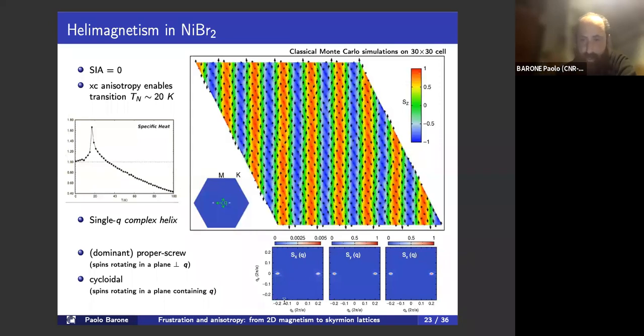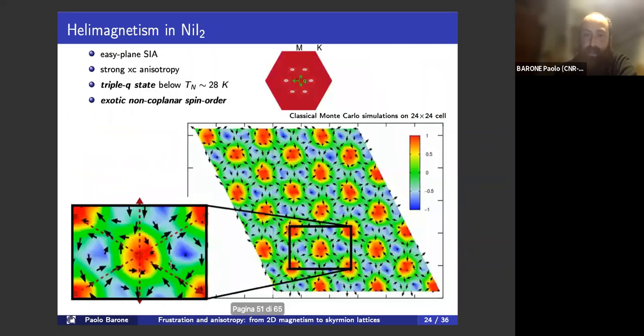But actually, we also found that there is a small cycloidal component, which emerges by decomposing the spin structure factor, from these peaks appearing in the x component of the spin structure factor. And this suggests that the presence of the exchange anisotropy is not trivial, so it's introducing some non-coplanarity also in the system. Now the non-coplanarity effect is even more evident in the case of nickel iodide.